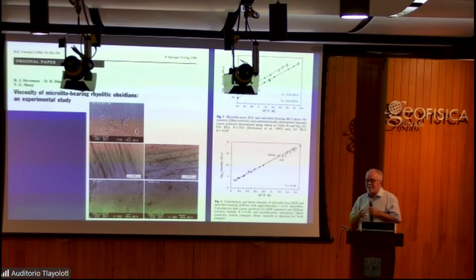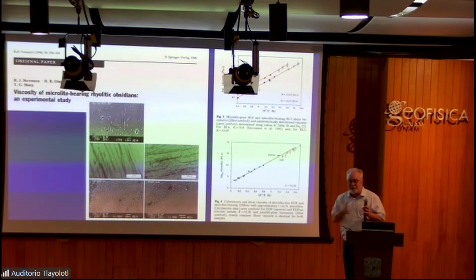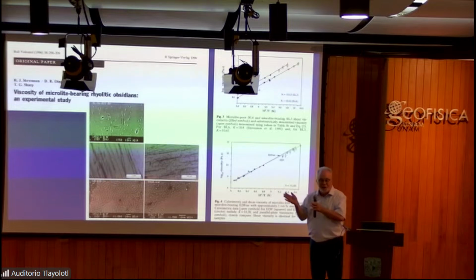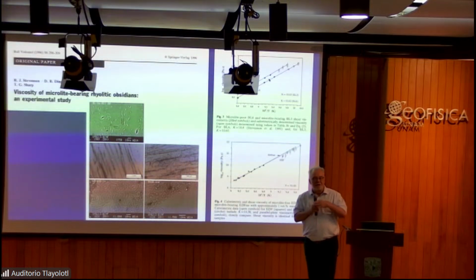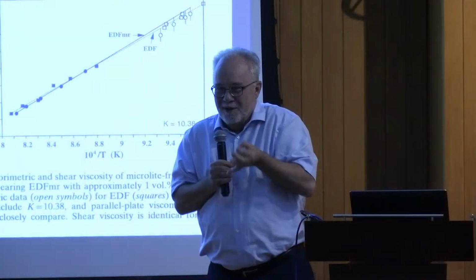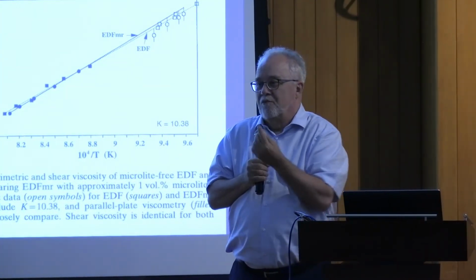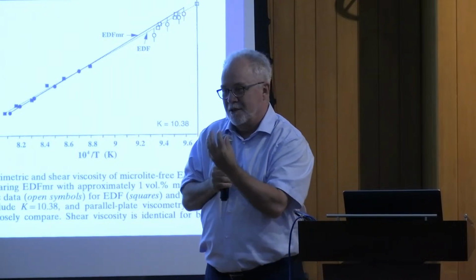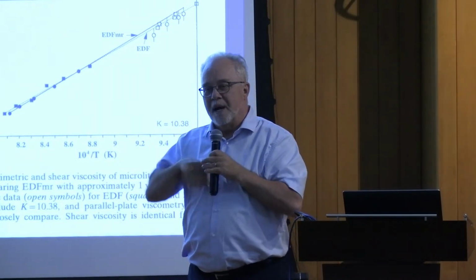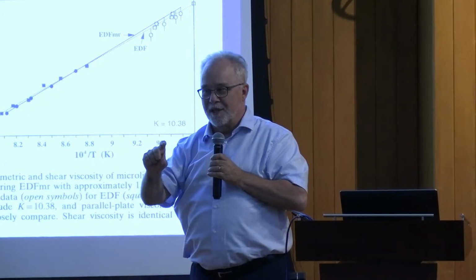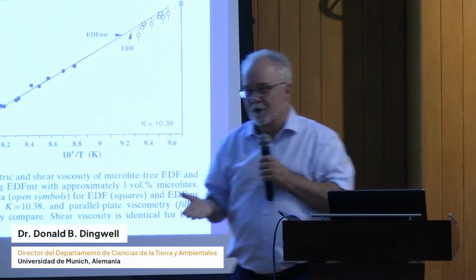I simply heat it up and measure its glass transition, because that gives me the viscosity, and the only thing contributing to the glass transition is the glass. The crystals are just along for the ride. They're sitting there before the glass transition. They're sitting there after the glass transition. They don't interfere with the glass transition. So you're surgically extracting, through calorimetry, a measurement of one phase in a horribly two-phase material, and then you can compare it to the bulk two-phase viscosity, and the difference must be the influence of the crystals.